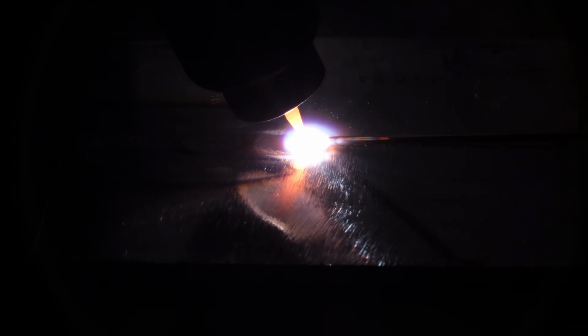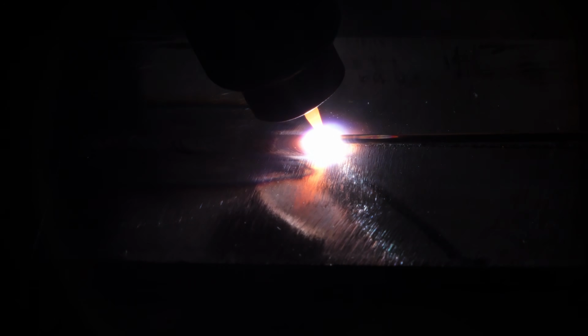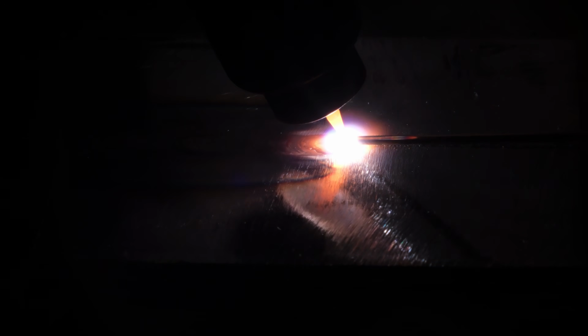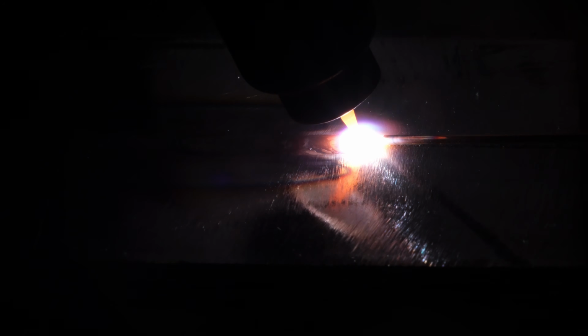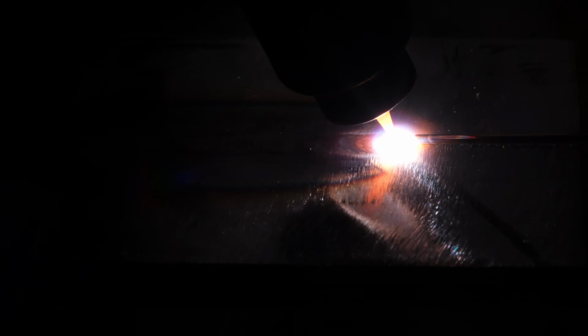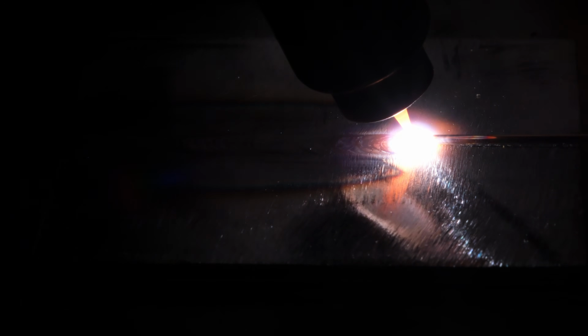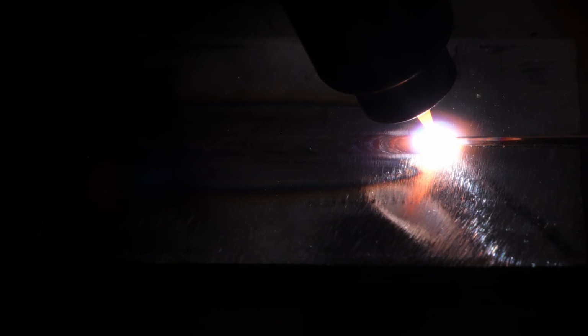I personally tend to retract the rod enough to where I can see where the two pieces of metal are joined. That way I know for a 100% fact that I'm fusing the root and getting some penetration. The main things that you need to focus on is just keeping a consistent arc gap and a consistent travel speed and a consistent filler metal addition. Now that I'm almost done with this, I'll play it one more time without any commenting. Oh, and I dipped it there too.